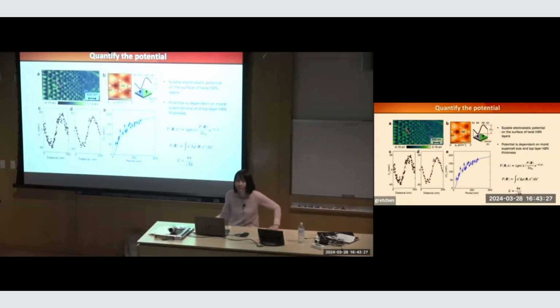Very impressive work. One question about the difference between gallium arsenide and the TMDs: people think there is a strong electron-hole exchange interaction in TMDs. Did you see any signatures of that? Yeah, actually, the excitons, you can put them in two valleys, right? The valley decay is very rapid because of the electron-hole exchange interaction. There are also different species of trion because of electron-hole exchange interaction. There are definitely many signatures of that. It's a little technical to get into.